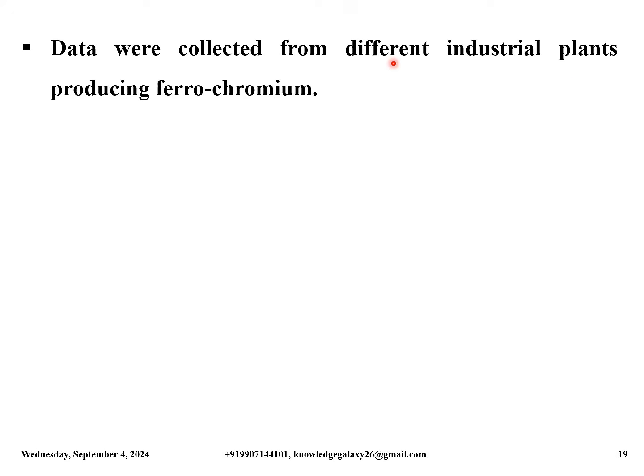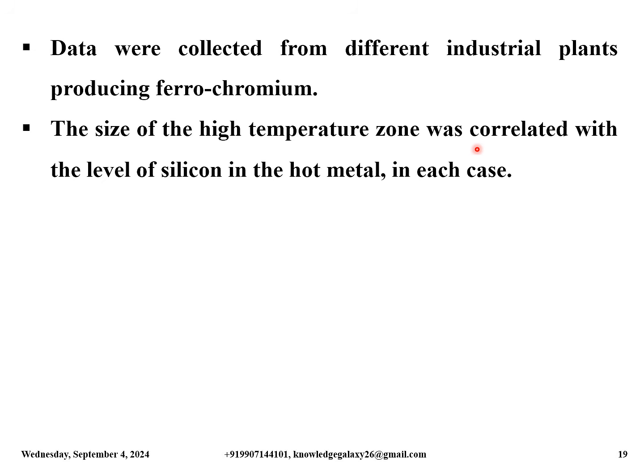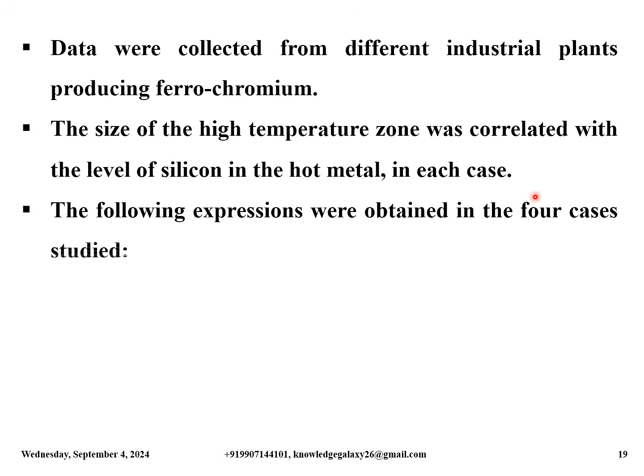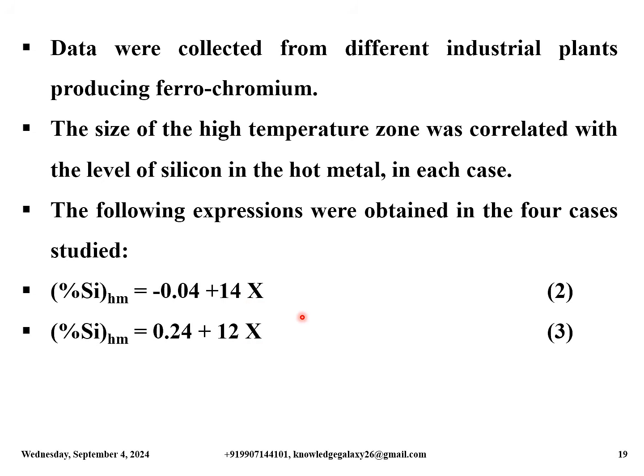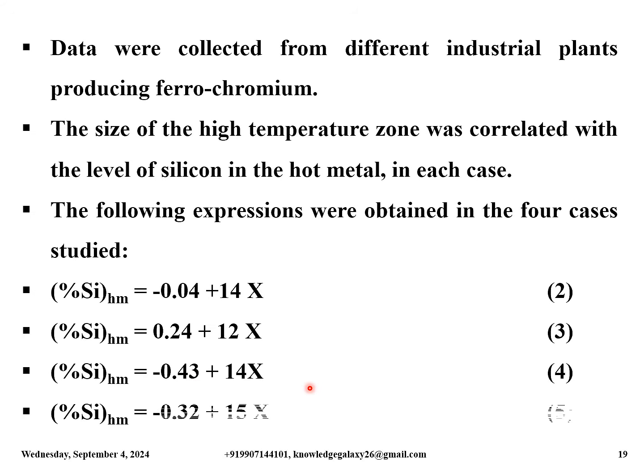Data were collected from different industrial plants producing ferrochromium. The size of the high temperature zone was correlated with the level of silicon in the hot metal in each case. The following expressions were obtained in the 4 cases studied. First one is percentage silicon hot metal is equal to minus 0.04 plus 14x. Next is percentage silicon hot metal is equal to 0.24 plus 12x. Next is percentage silicon hot metal is equal to minus 0.43 plus 14x. And percentage silicon hot metal is equal to minus 0.32 plus 15x.